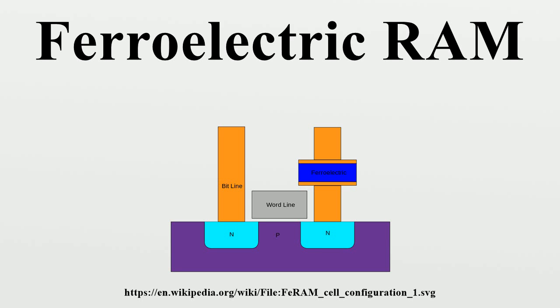However, the materials used to make FeRAMs are not commonly used in CMOS integrated circuit manufacturing. Both the PZT ferroelectric layer and the noble metals used for electrodes raise CMOS process compatibility and contamination issues. Texas Instruments has incorporated an amount of FeRAM memory into its MSP430 microcontrollers in its new FRAM series.